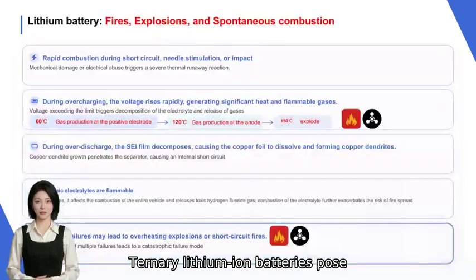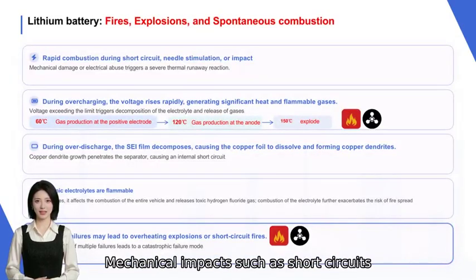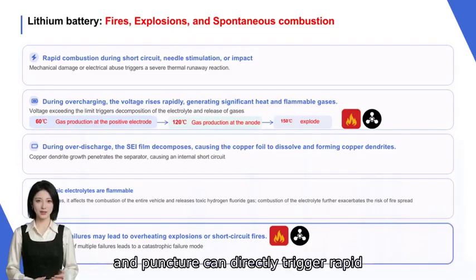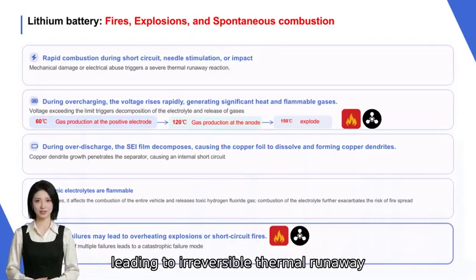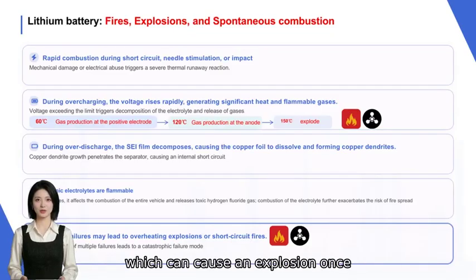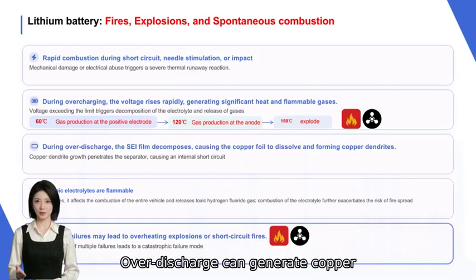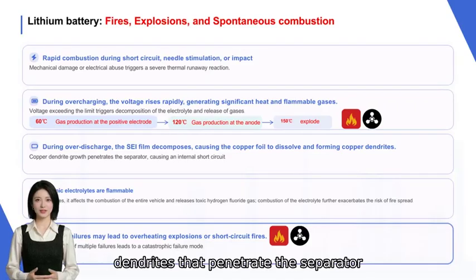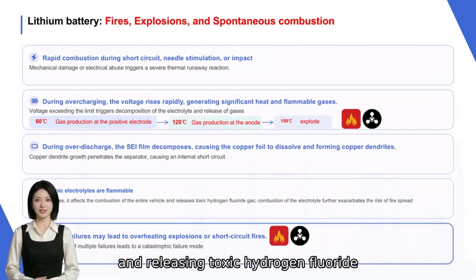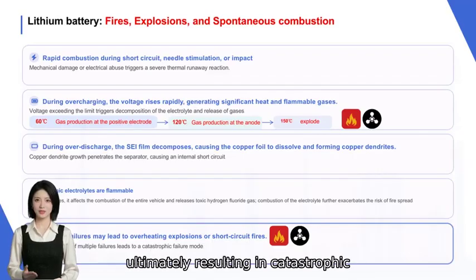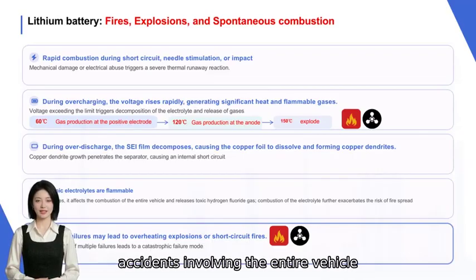Ternary lithium-ion batteries pose inherent safety risks. Mechanical impacts such as short circuits and puncture can directly trigger rapid combustion, leading to irreversible thermal runaway, which can cause an explosion once the temperature reaches 150 C. Over-discharge can generate copper dendrites that penetrate the separator, causing an internal short circuit and releasing toxic hydrogen fluoride, ultimately resulting in catastrophic accidents involving the entire vehicle catching fire.